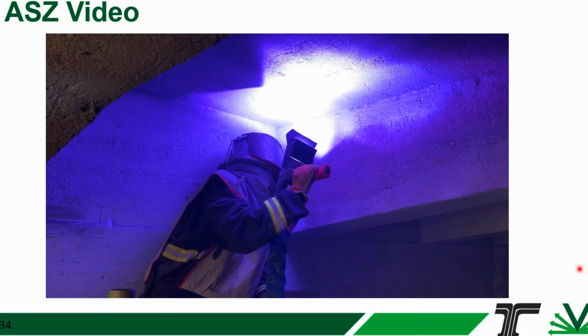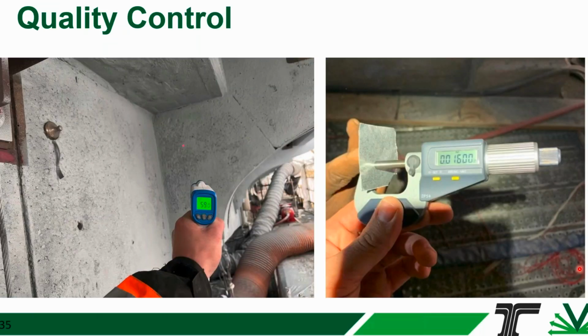Quality control is really important in these projects. On the left, what's being measured is the temperature of the concrete surface. You're going to want to measure the temperature of the concrete surface as well as the humidity. That's important to make sure that you're well above the dew point, because you're spraying hot zinc onto the concrete surface. So if there's moisture there, it's going to vaporize and give you problems with